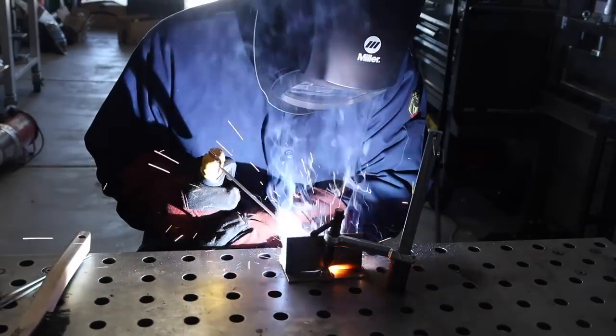One, having those spots where it hasn't fused to both sides of the plate is a really common issue with 6013, and it's caused because the slag mixes in with the weld pool and gets in the way. Two, if you want to make sure you're avoiding that while you're welding, you need to look and make sure that you can see the weld puddle and a boundary to the slag behind it. And three, in order to avoid it, you need to increase amperage usually, and increasing the rod angle a little bit will help you out also.